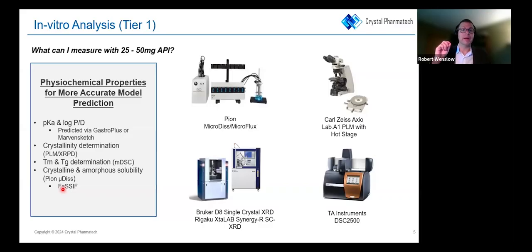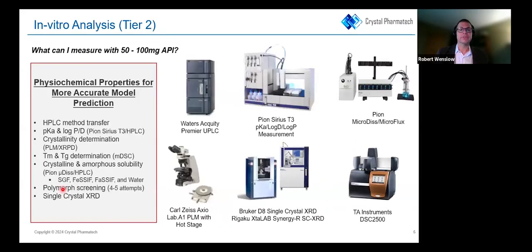And if you have the amorphous compared to that, then you can get the potential advantage of using the amorphous over the crystalline. And then you start using the GastroPlus to start understanding what your PK profiles would be with an amorphous material compared to a crystalline material. When you start having a little more material, then things get a little bit better, and you can then start getting accurate log P, pKa.